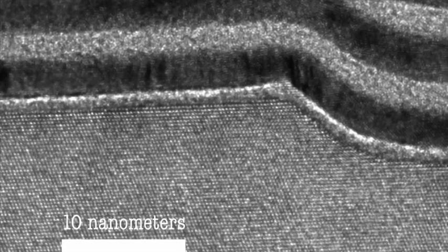There are two unique new aspects of this work. One is the fact that we've improved an existing process, which is the production of the substrates — these silicon substrates which have atomically perfect terraces. That was an existing process, and it worked to some extent, and we found out how to make it essentially perfectly, so all of the atoms in one facet are in a single plane. And if you look at a cross-section of one of these gratings with transmission electron microscopy, it is amazing — more or less every atom is in the right place.